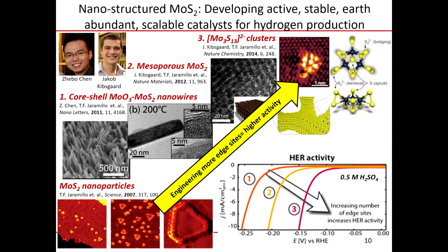turned out to be pretty good catalysts in acid. And so this is work as a postdoc, working with Ib Chorkendorff and others at the Technical University of Denmark. And then my research group at Stanford developing all kinds of different formulations of sulfides. As you can see, nanowires, nanoporous materials, small molecular clusters. These are Zhebo and Jakob, one of the first PhD students and postdocs to join the group. And these were very active. And we were very excited, non-precious metal catalysts.